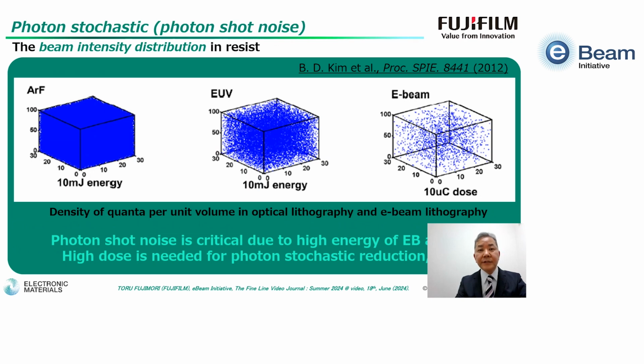The beam intensity distribution in resist compared for ArF, EUV, and EB. In the case of EUV, about 14 times fewer photons than ArF. And also in the case of EB, more and more fewer than EUV. So photon shot noise is critical due to the high energy of EB and EUV. High dose is needed for photon stochastic reduction, but there is a trade-off with sensitivity, like the writing time.